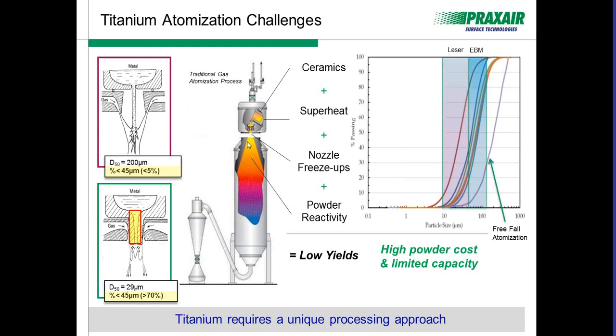When you move to the closed coupled technology, you can really maximize that yield. And these are some size distributions that we were able to perform and look at here. And you can actually maintain it within the laser size range. As I said before, these are some experimental data that we've been willing to publish, and you can maintain around 70% yield when operating correctly.